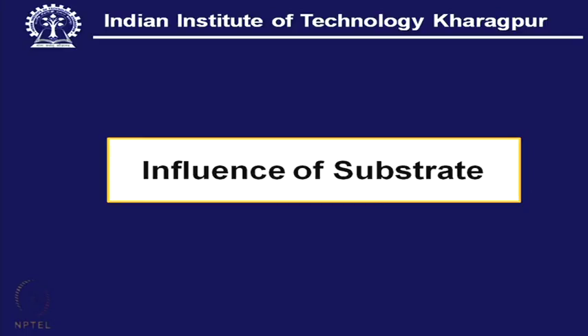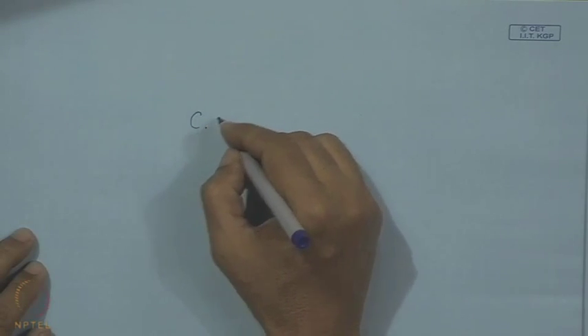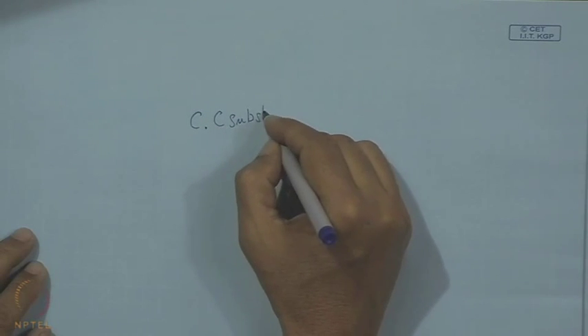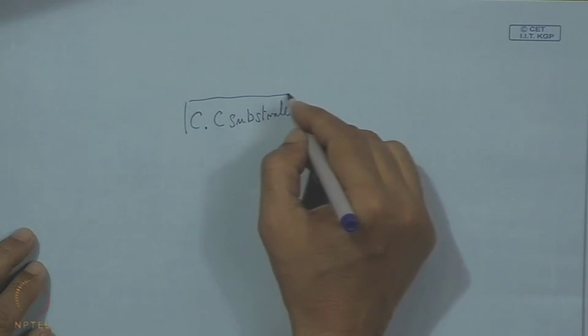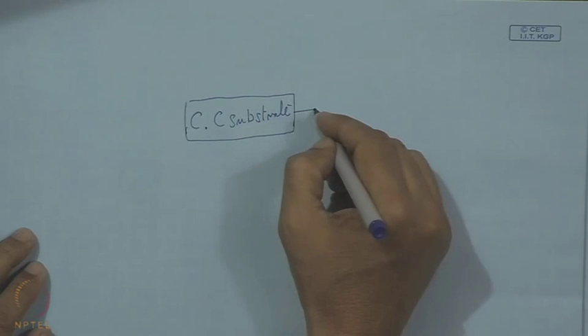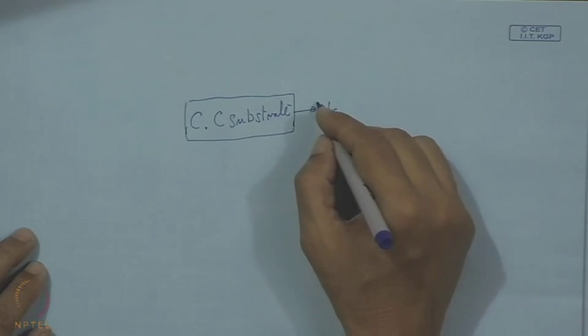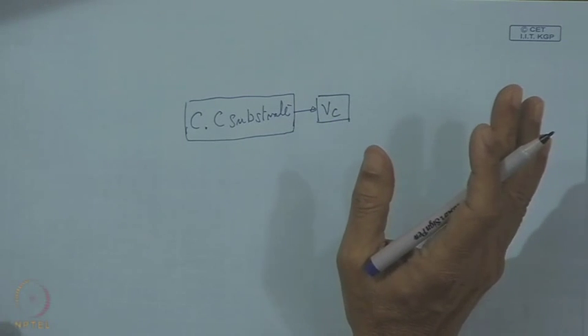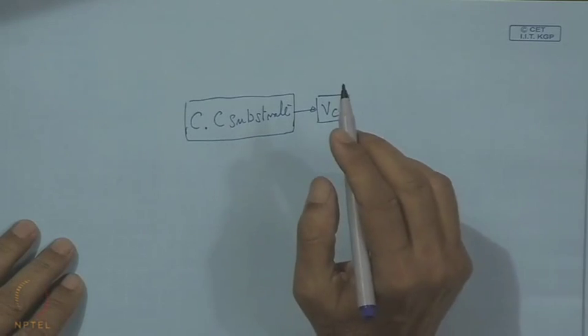Now comes a very important issue, that means the influence of the substrate. Now, we see that this aluminium oxide coating happens to be one of the very prospective candidates to be used with tungsten carbide substrate, that means what we call cemented carbide substrate. This is going to be used in a cutting tool, which can be used with a higher process parameter, that means higher cutting velocity. So, that is the aim of the whole work, to have this coating on cemented carbide substrate.